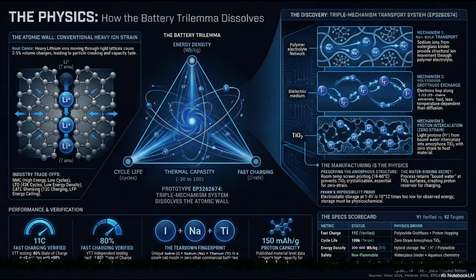So if you try to shove lithium ions in too fast, say trying a high-speed charge rate at a comfortable 30 degrees Celsius on a thick, energy-dense electrode, the lithium literally cannot penetrate the material fast enough. It's a traffic jam at the atomic level. And when the lithium can't get inside the anode quickly enough, it just piles up on the outside of the anode. That is a phenomenon called lithium plating. Which is disastrous. It causes massive, irreversible capacity loss.